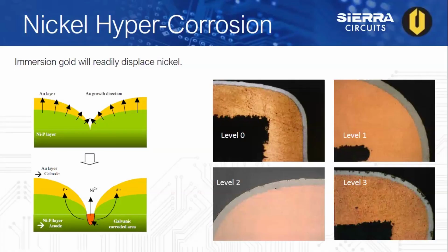I'll jump to the last one, level 3. The number of spike defects is over 10, taking up 40% of the nickel deposit thickness, or if you also see a black band observed extending 30% of the field of the cross section. I skipped level 2 because IPC specifies that level 2 is categorized as anything between level 1 and level 3. But if you reference IPC, that's what you'll see.